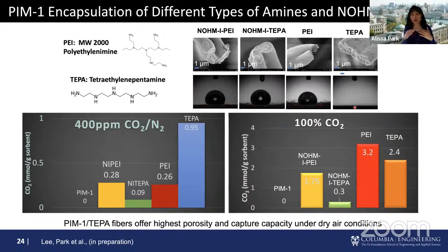The reason is the way we make electrospun fibers, TEPA was too tiny, very short, a smaller amine polymer, so that it was migrating towards the surface. And you can kind of see in these SEM images that on the surface, the TEPA was exposed, making the surface hydrophilic. So if you want to selectively reject water during direct air capture, definitely TEPA is not the good option, but NOHM-based system seems to be fantastic at keeping it hydrophobic while keeping all the NOHM-based CO2 capture materials encapsulated within this fiber system.